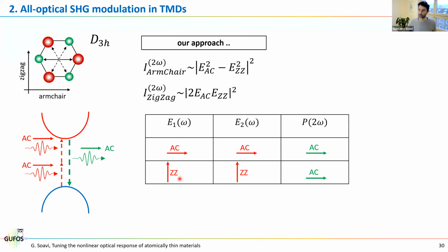Now, let me put this into a table that is probably easier. Whenever you do a second harmonic experiment, you typically use only one pulse. So the two photons are from the same pulse. And now these two photons can either be aligned along the armchair direction. And so if you see here, the zigzag is 0 and everything is emitted along armchair, or they will be both along the zigzag. In this case, armchair is 0 and everything again is emitted along armchair.